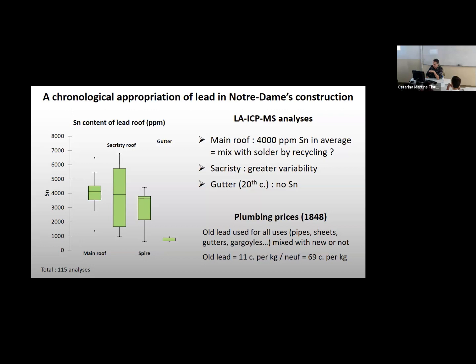And one element which can be used to trace the recycling is tin, because tin is an element which is present in soldering. Soldering is made of a mixture of lead and tin. Usually it's 1/3, 2/3. It can be a bit different, half, something like this. So soldering was used, and when you recycle your lead, you would not take the soldering out, and you would mix the soldering with the lead, and then your content of tin in the recycled lead increases. So in a new lead, you have no tin at all. And when you start to have some tin, it can mean that there's been some recycling.